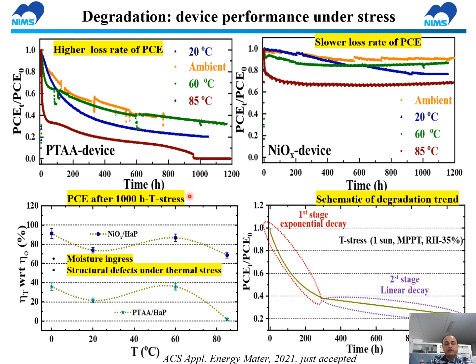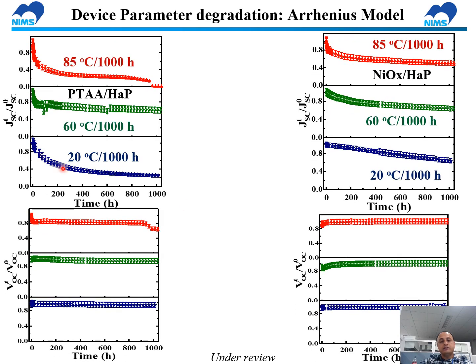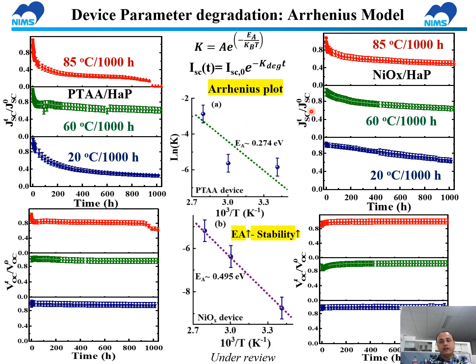And we have to explore the degradation kinetics to understand the degradation mechanism, and for the degradation kinetics, we use the Arrhenius model. We fit the JSC degradation trend of each device under each thermal stress, and then by analyzing the Arrhenius plot, we estimated the activation energy of degradation of each device. We found higher activation energy for degradation for the nickel oxide device. This suggests that nickel oxide has better stability, because higher degradation activation energy is better for stability.